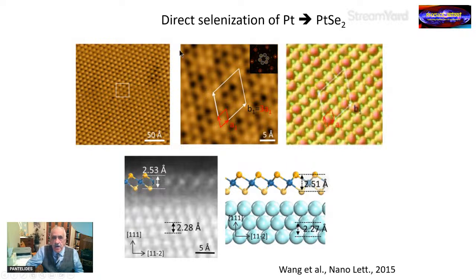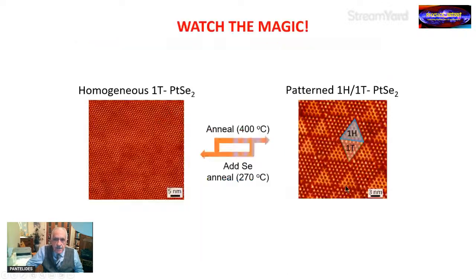You just put selenium on platinum, and then you heat it a little bit, and you get this material. It took us a long time to figure out what the material is. We had to do a STEM image from the side, so we could see the substrate and the monolayer of platinum diselenide at the top. It was published in 2015.